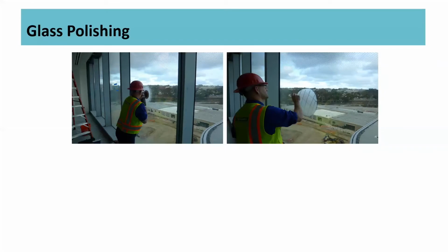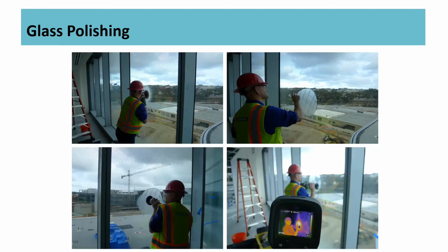You can see the operator in this case using a handheld polisher with some sanding discs on the end that have a variety of grit to them. Starting out with very coarse grit and moving to fine grit, the operator first of all gets to the bottom of the scratch and then feathers that area out to the adjacent unpolished areas. We also, as a precaution, take the surface temperature of the glass during these operations. Rarely does it get up to 300 degrees, which is much lower than, say, even heat soaking glass. So there's no real danger of real stress relaxation of heat treated glass products. And now I would like to show a video of this in operation.